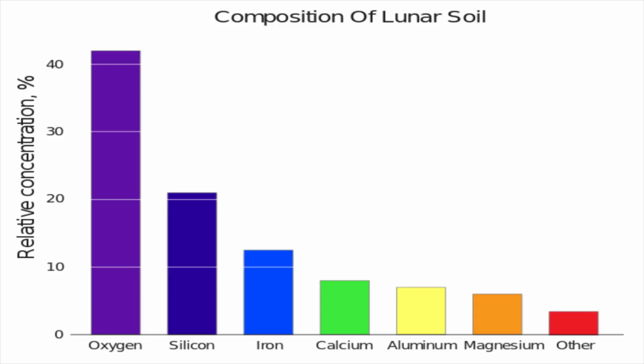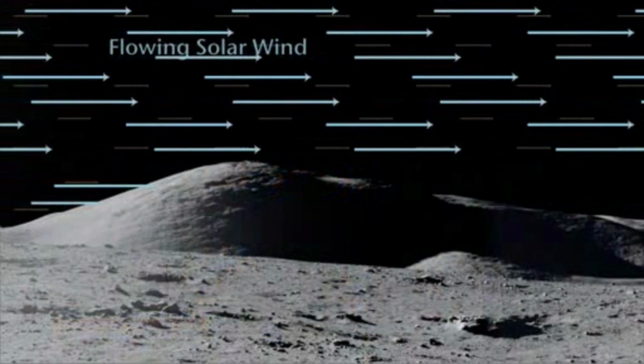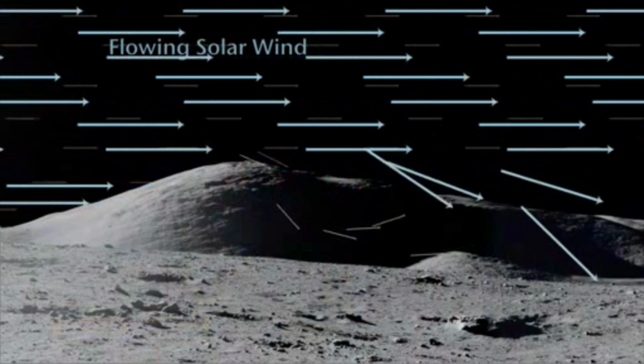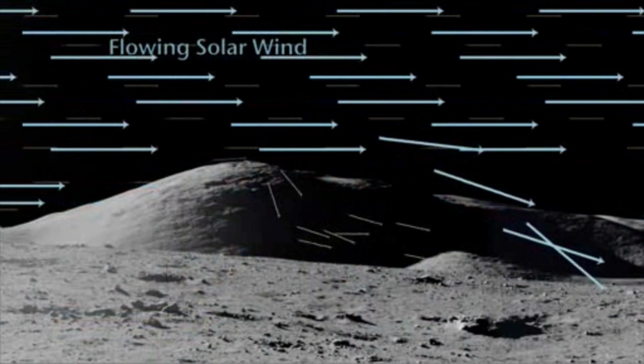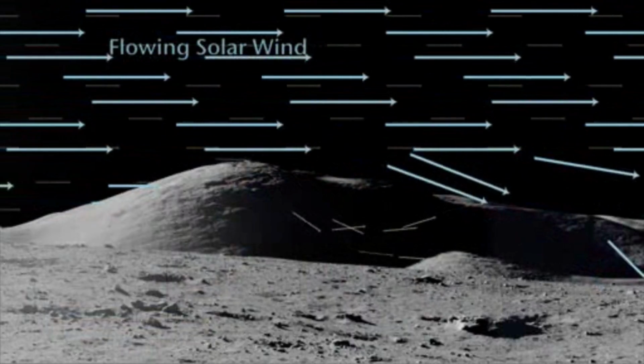Iron oxide, or rust, is abundant on the moon. For nanophase iron to form, this rust must lose its oxygen atom. How this happens is not fully understood. The possible reason suggested in this study is that the solar wind reacts with the oxygen in the iron oxide within the regolith to form hydroxide and water molecules. These molecules diffuse through the regolith until they reach the coldest part of the moon, the lunar poles, leaving behind only pure iron.